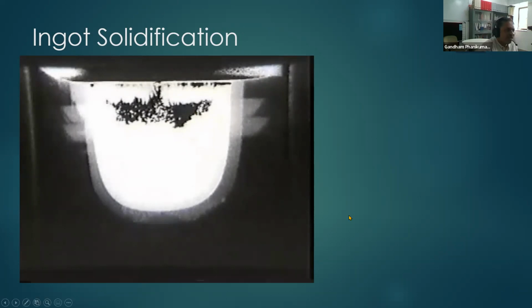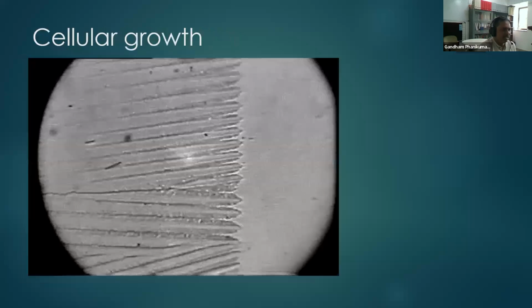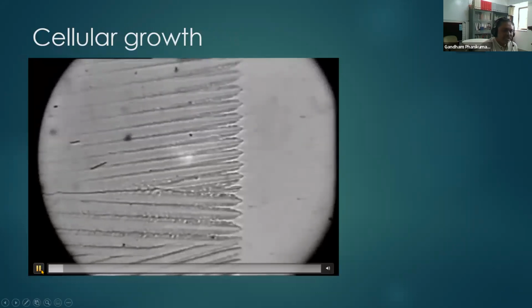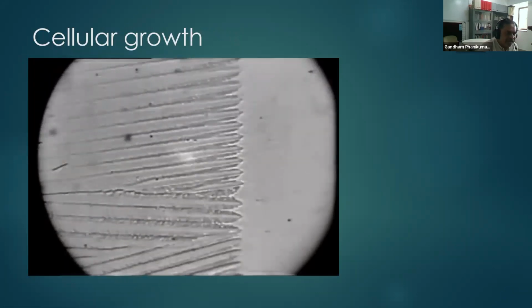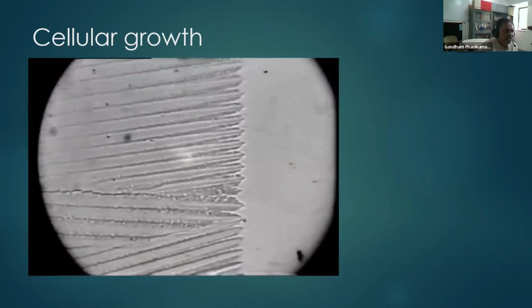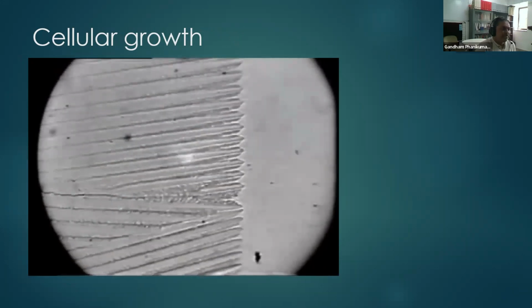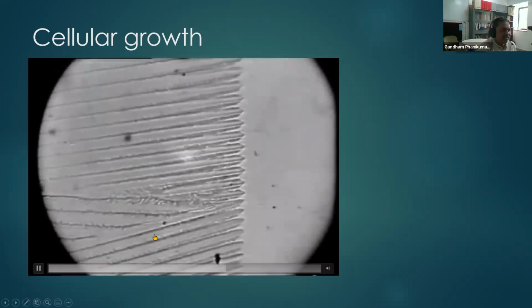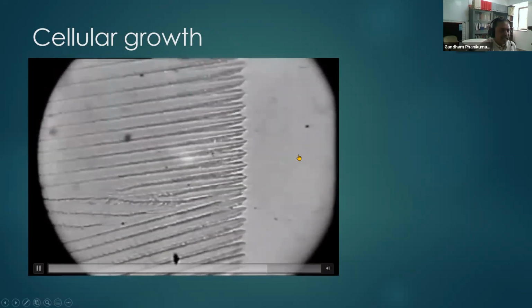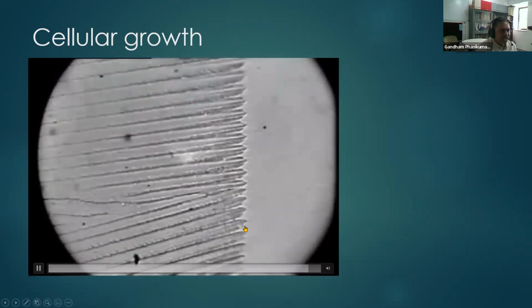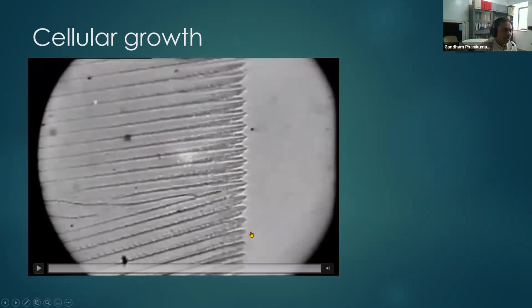Okay, so you can think of the laser molten pool as a tiny ingot, and therefore learning about how an ingot solidifies is going to be useful for us to explain. Now, many times we see microstructures in additive manufacturing with a cellular appearance. That is, they appear like cells, tiny regions of uniform spacing. And the reason why it happens is that the solid front is moving in the liquid to grow, and it moves as a cellular front due to the solidification microstructure evolution caused by the so-called Mullins-Sekerka instability.